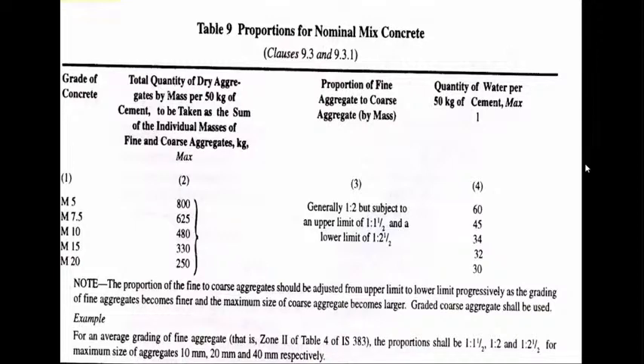So when you are at the top, the fine aggregate should be the coarsest. So if you have a very coarse fine aggregate, then you should use 1:1.5. If you have a normal zone 2 classification fine aggregate, use 1:2. If you have a very fine sand, then you should use 1:2.5 as the ratio to proportion fine aggregate. So the proportion of the fine aggregate to coarse is adjusted from upper limit to lower limit progressively as the grading of fine aggregates becomes finer, and also as the maximum size of a coarse aggregate becomes larger, which means the general ratio of 1:2 is applicable for zone 2 classification sand and also 20 mm nominal size of aggregate.